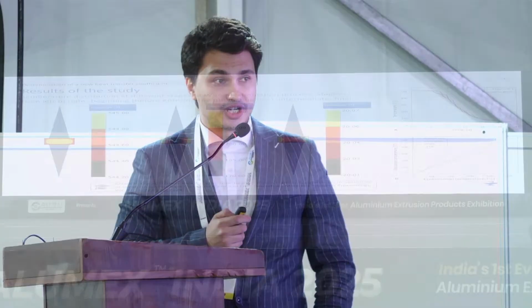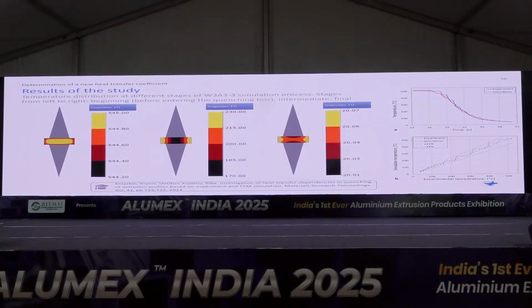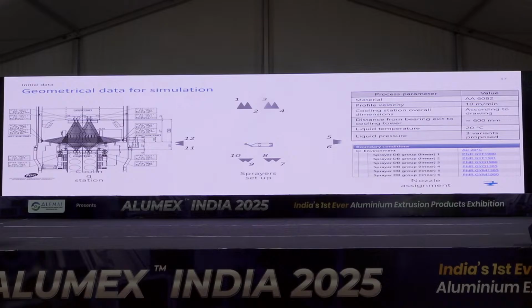And here you can see that once we finished the project and customized our new heat transfer coefficient, the result matches reality considering the cooling rate. So it means that potentially we can virtually simulate the quenching process to predict the needed cooling rate, and potentially the deformation of the profile, with an accurately predicted cooling rate. In order to set up such a type of simulation, you will need to do the following. The first thing is to create the model for the quenching station.